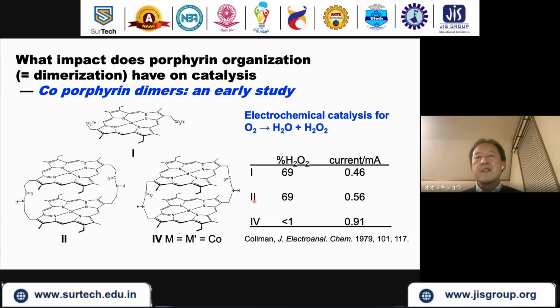And for this dimer, H2O2 is about 70%, and the current is about the same as the monomer. So there is a little dimerization effect, but this dimer is very similar to this one, with a slight difference in the bridge part. The number of carbon atoms here and here are different, and then a dramatic effect was observed. Percent H2O2 is less than 1%, which means more than 99% of the reaction results in the production of H2O, not H2O2, and the current also increases.